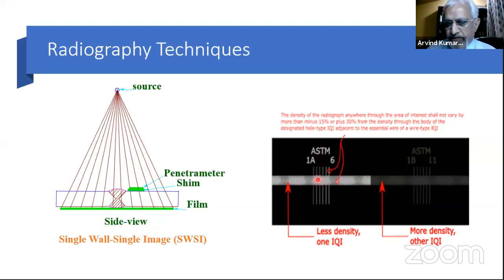This is the IQI, the image quality indicator. You can see, maybe this is an X-ray, and you are able to see all the 6 wires or 7 wires which are available. So based on the thickness of the last wire and my job thickness, I can calculate the sensitivity that I've got.